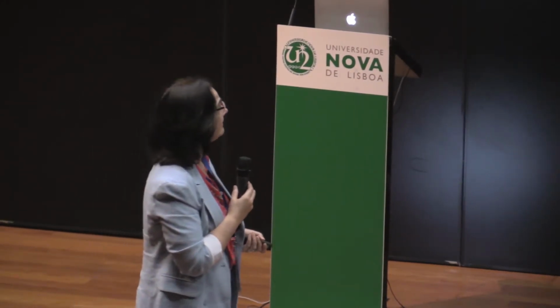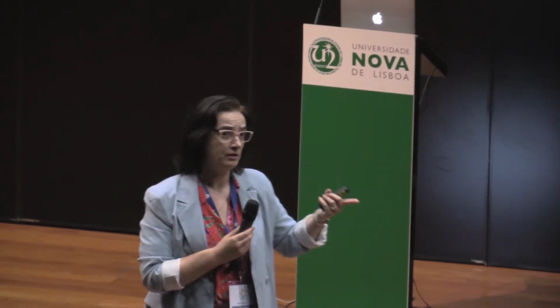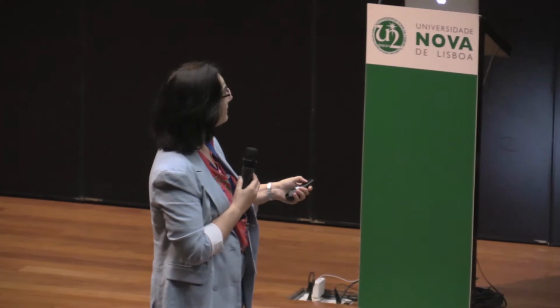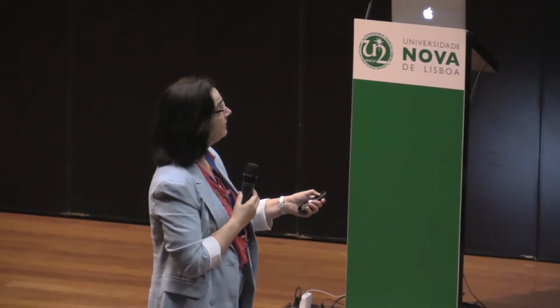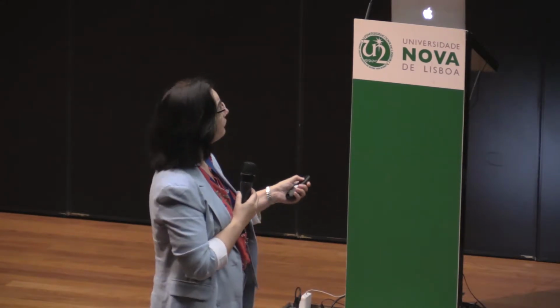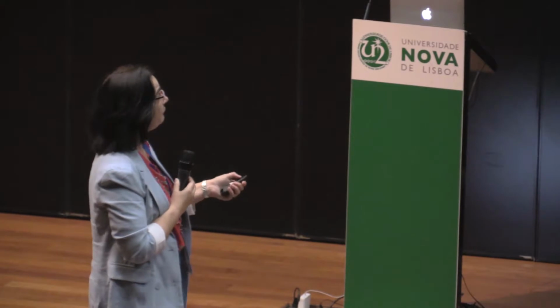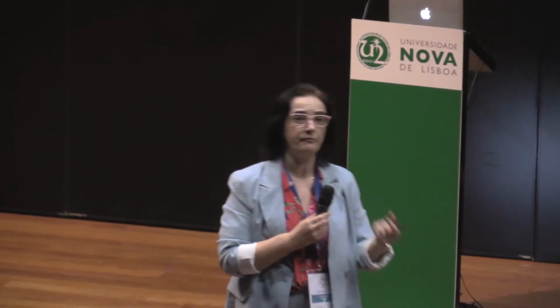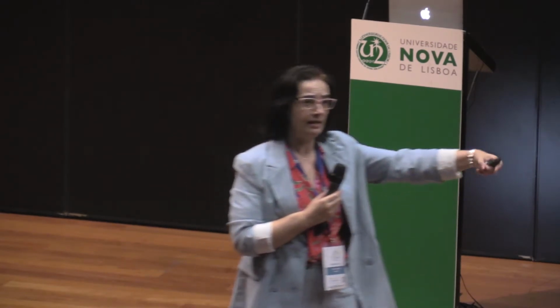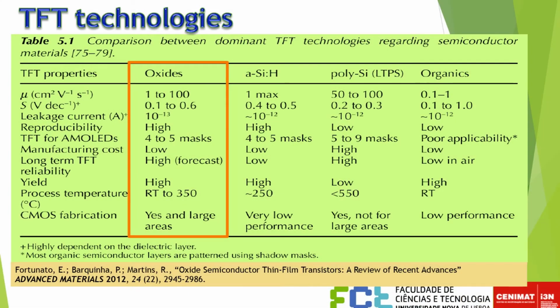Here I present a table where we compare the different technologies commercially available today: oxides, amorphous silicon, the one that is still used, polycrystalline silicon, and also organics. If we compare some of the main properties required for display applications in a thin film transistor, take a look at the mobility, which is like a figure of merit. If we want to compare devices made with different materials, usually mobility is the property we are looking for. For oxides, we can reach values up to 100 square centimeters per volt per second. For amorphous silicon, the maximum value is around 1. So we can increase the electrical mobility by 2 orders of magnitude.